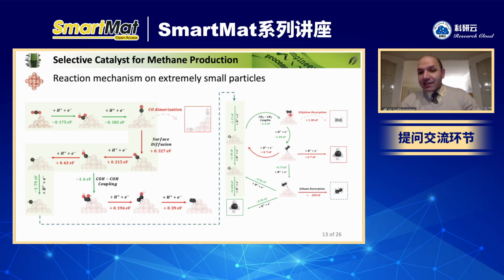But what happens is that the ethylene sticks there and doesn't really leave the surface, because it is strongly adsorbed, perhaps because of the shape of the surface. I assume these particles are very low coordinated, so there is more electron density around them, and they can create a stronger chemical bond. This is what we observe from the charge localization and charge distribution through DFT. Once the ethylene remains there, it can be further protonated, and you see there is almost no energy barrier, and then even further until you get ethane.